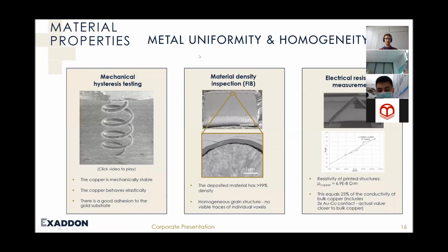Crucially, the mechanical properties of our metal objects are very sound. In mechanical hysteresis testing, we can see that the printed copper is very elastic, it's mechanically stable, and there's excellent adhesion to the gold substrate.